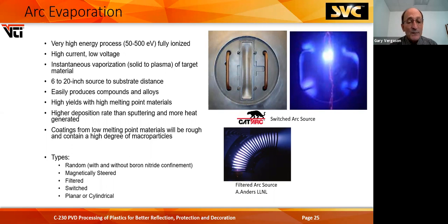Higher deposition rate than sputtering, but again, more heat is generated. And coatings from low melting point materials will be rough. And there's several types of configurations. You can have a random arc where you're not trying to magnetically steer it or switch it. Magnetically steered, where you're driving it around with a magnetic circuit on the back of it. This happens to be a filtered arc, courtesy of Andre Anders from Lawrence Livermore.